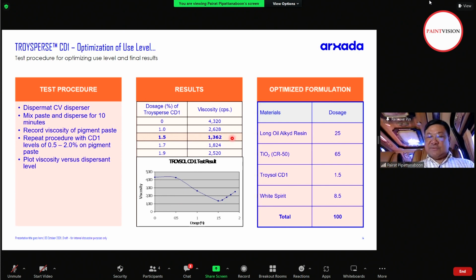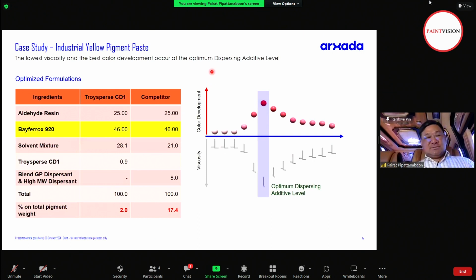And then we ran with this formulation, stabilized it, and then checked the L value. It gives you the highest L value for the white TiO2 pigment paste. Another test that we ran, we checked with Bayferrox 920 pigment yellow oxide, 46% loading.